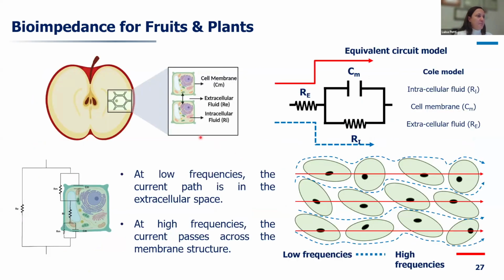So a typical fitting of a component like an apple is a so-called Cole model, which takes into account the resistance due to the intracellular fluid, the capacitance of the membrane, and the resistance of the extracellular fluid, which actually has different behaviors at different frequencies. So at low frequencies, the current path is in the extracellular space, what you see here in blue, whereas at high frequency the current can pass through the membrane structure. So you can see different things at different frequencies.